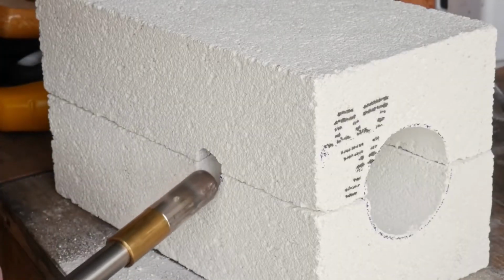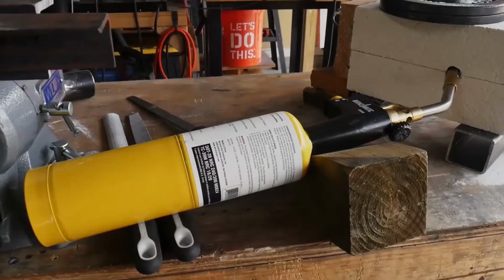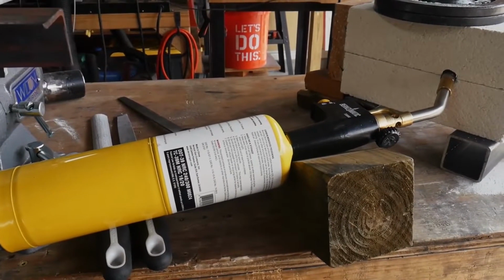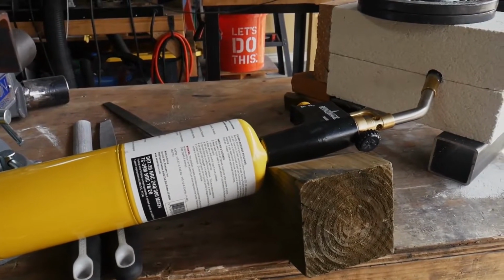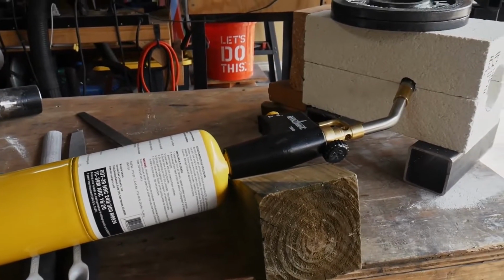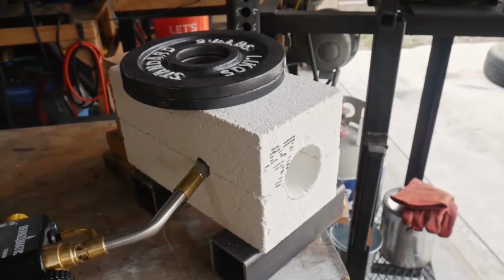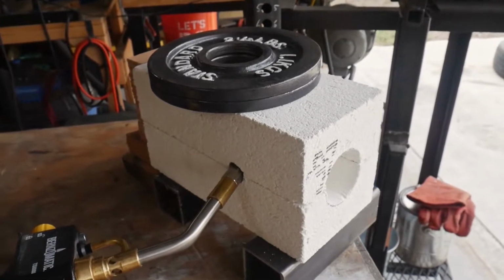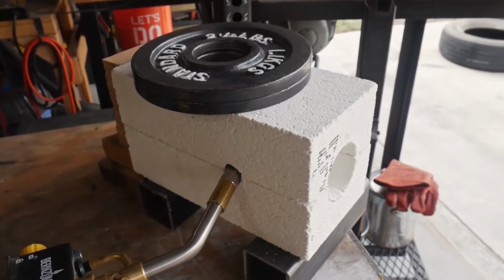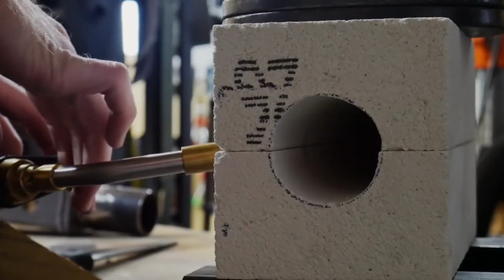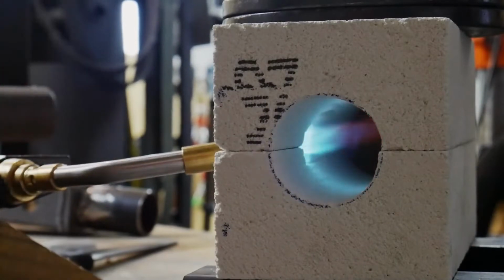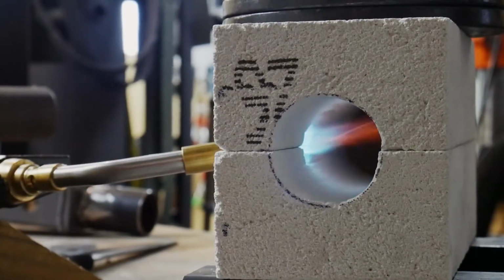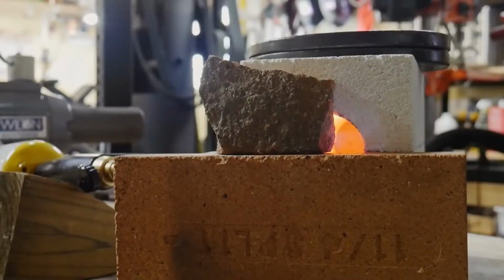I took the forge and put it up on 2 blocks. I put a weight on top to make sure the 2 pieces stay together, and I took some old fire brick I had to block off the back of the forge. You can see that the Bernzomatic MAPP gas burner is pointed into the forge at a very slight angle. So this is the initial startup. I was actually quite impressed on how little time it took for this little forge to heat up.